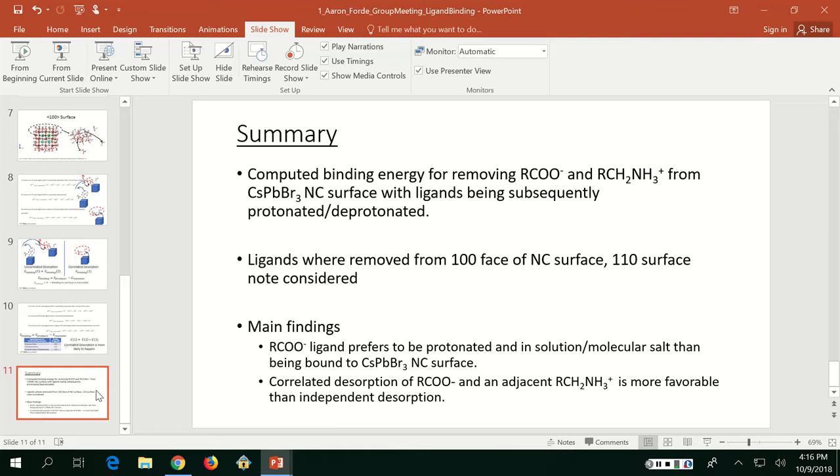Very broadly, these are a relatively new class of systems. They were first synthesized in 2015, and there are still a lot of open questions about their surface chemistry. There are reports from NMR experiments where you can track the ligand passivation of these things. And experimentally, they find that it's a dynamic bonding of the anion or the acid, constantly popping onto the surface and coming off. And so it's part of the decomposition process, I would suspect, through protonation.